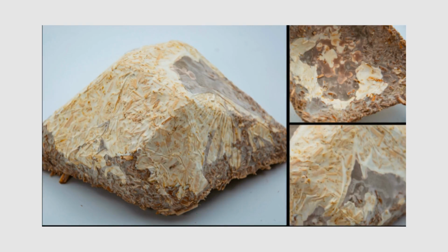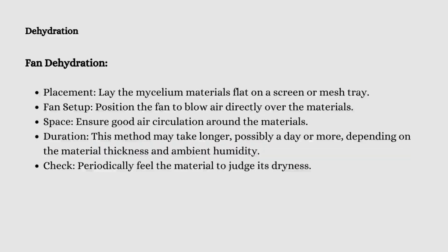And that's likely going to happen if you leave this growing for longer than the period of time that you want this to be growing for. Normally it's fully grown when it's all white, and there you can stop the growth process. If you leave it any longer, it's going to start to create these secondary metabolites. It's sometimes going to have a little bit of a yellow ooziness to it, and that's also okay. That's just these secondary metabolites at work.